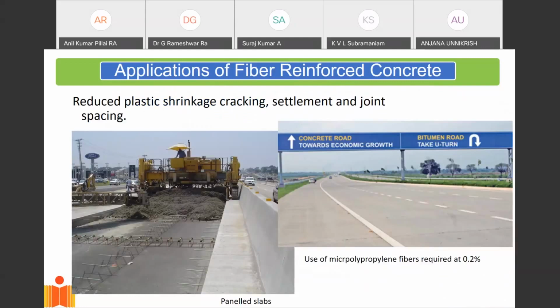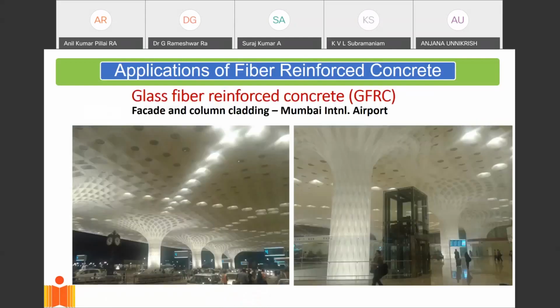The other area where fibers are finding big use is small synthetic fibers being used to cut down on cracking in concrete. Oftentimes, concrete cracks because of shrinkage, where when concrete starts drying, it cracks. And even sometimes curing doesn't help when these cracks develop. So basically, the use of micropolypropylene fibers, these are very, very fine fibers made of polypropylene, which are added to concrete at a very small dosage of about 0.2% of the volume of concrete. And they're able to mitigate these cracks that form in concrete. And glass fibers have been used extensively for architectural concrete because they're able to cut down on the appearance of the surface cracks that come when concrete dries.